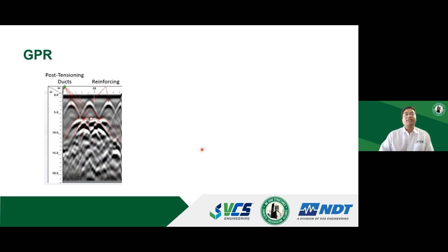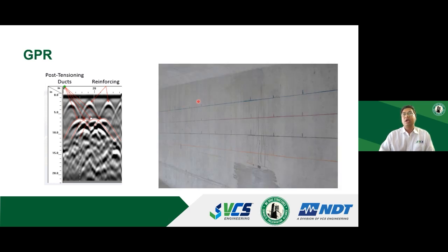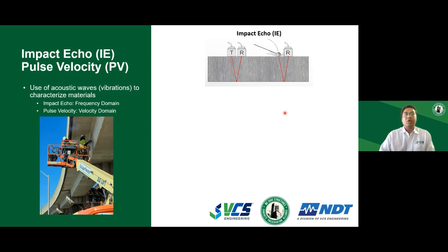To an experienced eye, it's easy to discern between the reinforcing steel and the post-tensioning ducts just by looking at the contrast signatures or the peak signatures. And once you do the GPR scans, you just lay out the drape of the tendon to track the profile of the tendon. And we mark that profile every 1 foot for subsequent testing using maybe sonic or some other testing. So once you lay out the profile of the tendon, you often use sonic or ultrasonic. We call it impact echo or pulse velocity technique.